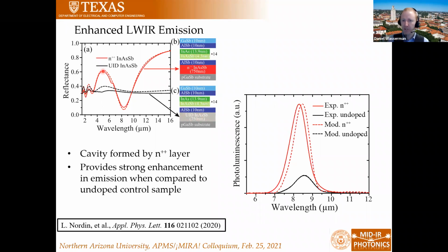So if we look at the reflection, what we see from the undoped sample is basically just a flat reflection, which is what you'd expect because the refractive index for undoped material is basically 3.5. And so you're basically looking at reflection from a dielectric surface, a high index dielectric surface. You would expect about 30% reflection. And our simulations bear that up. The simulations are here in the dashed. But if we look at our plasmonic system, what you see is this rather strong feature here at about 8.5 microns. And this corresponds to essentially a cavity mode that's set up in your system because you have effectively a plasmonic, a reflecting layer, and then a thin dielectric layer on top of that. And so what you get is essentially a thin film interference effect or a leaky cavity.